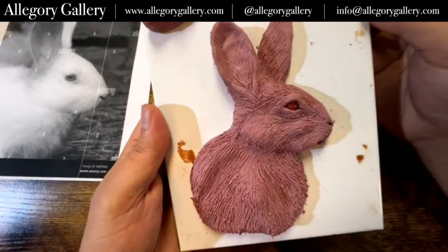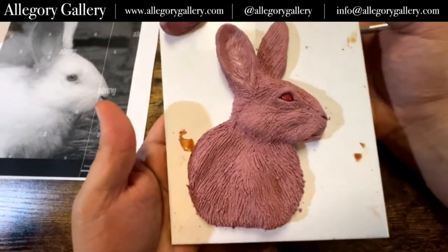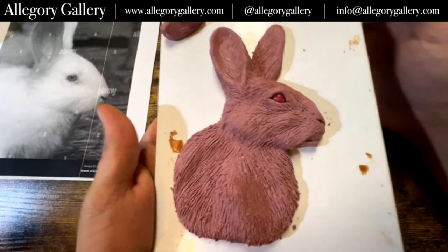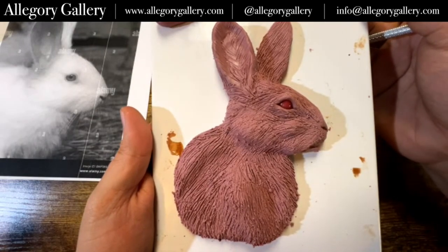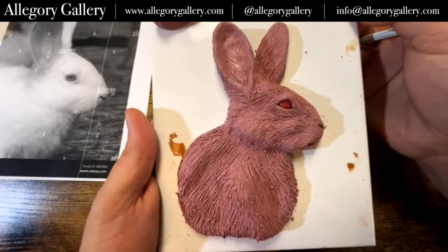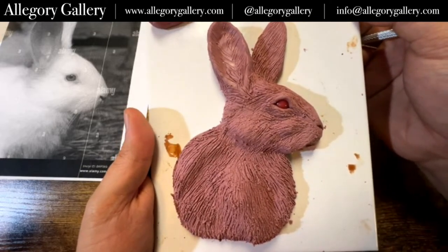And then, so we're pretty much done. I'm going to put this in the oven. So for firing or curing here, I skipped this part and I probably should have mentioned it. For curing, it's 275, 15 minutes for every quarter inch thickness. So in theory, I can get the calipers out and gently measure this, and we can think about this all day.